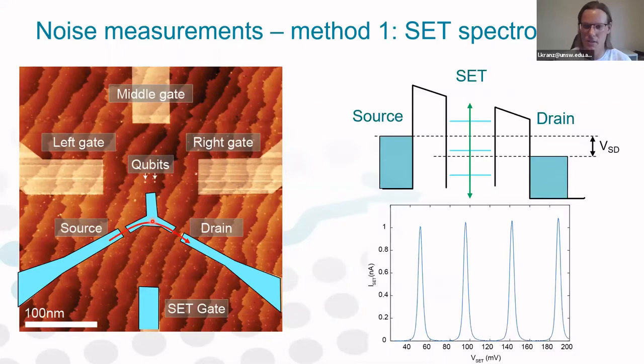So first, let me explain briefly the working principle of a charge sensor. If we take the energy diagram along this red line here, we have a source filled up to Fermi energy. Then we have a tunnel gap. Then we have the SET, which can be understood as a quantum dot with quantized energy levels. Next, we have another tunnel gap, and then the drain. Now, when we apply a bias voltage between source and the drain, we can force electrons to tunnel between source and the drain via the SET.